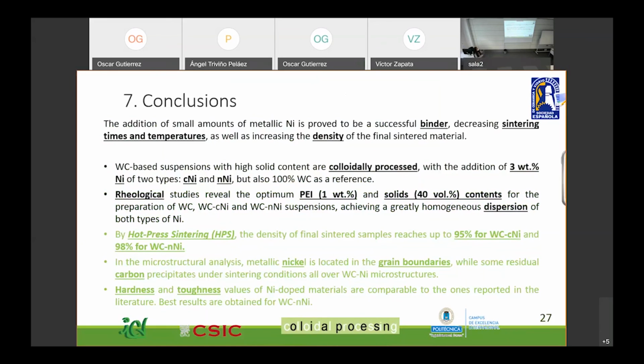Rheology revealed that the optimum amount of dispersant was 1% in weight, and the solid content for both our suspensions was 40% in volume, sorry, for the preparation of our slurries, and they achieved a greatly homogeneous dispersion of both types of nickel. By hot press sintering, the density of the final sintered samples reaches more than 95% for the mixture with commercial nickel, and even more than 98% for the mixture with nanometric nickel.